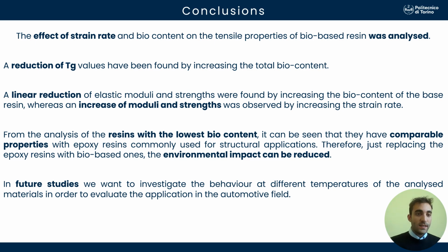So, finally, the effect of the strain rate and the bio content on the tensile properties of bio-based resin was analyzed in this study. And in conclusion, we can say that a reduction of the glass transition temperature values has been found by increasing the total bio content. Moreover, a linear reduction of elastic modulus and strength was found by increasing the bio content of the base resin, whereas an increase of modulus and strength was observed by increasing the strain rate.